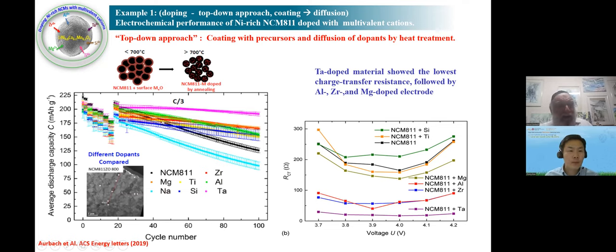And we see that in certain cases, if we take the black and look at capacity versus cycle number in galvanostatic cycling, we see very clearly that if the black here is the reference, some dopants, like in this case tantalum, provide quite stable behavior, which is well reflected by the structure through XRD, but I don't want to discuss this slide now.